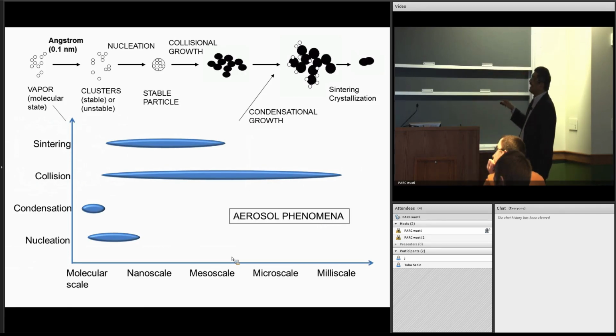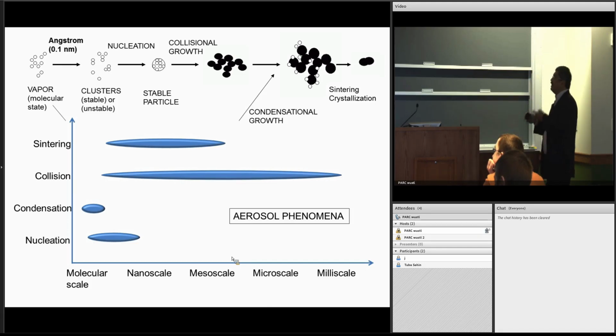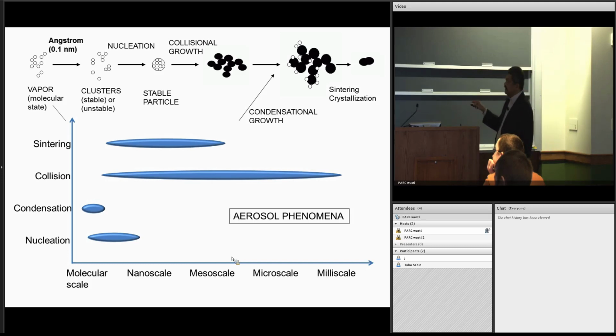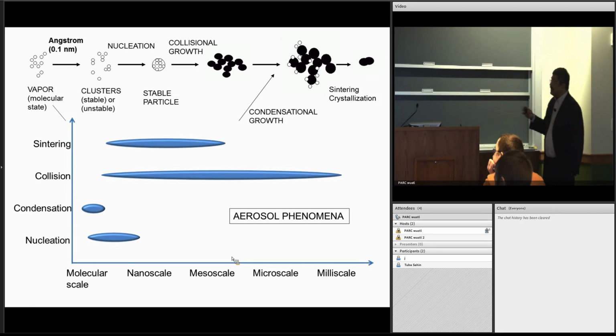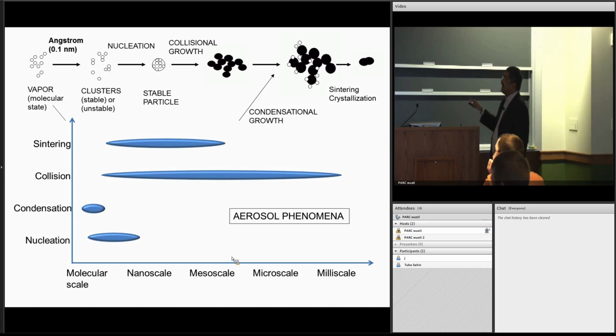So here, these are the scales over which I might have to deal with this problem. Start with the molecular scale, nucleation. This initial step is known as nucleation, moving from a molecular state to a cluster state, and it is extremely complex in high temperature environments. Until today, we don't understand this very well from a theoretical perspective. Experimentally, we are designing instruments to really measure this and map these rates out. Then condensation, the molecules could condense on an existing particle, and this would result in growth.